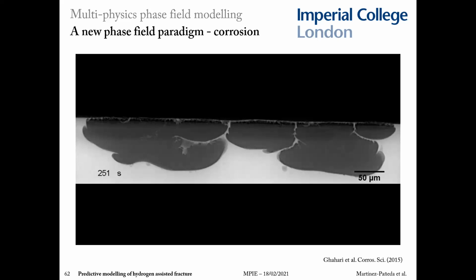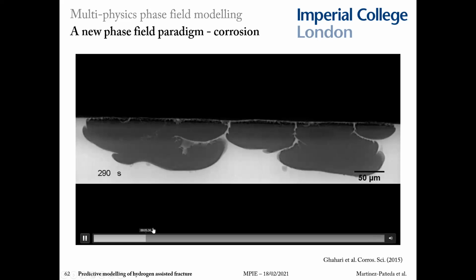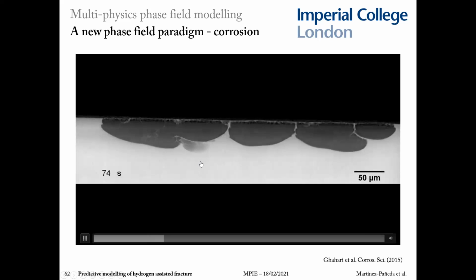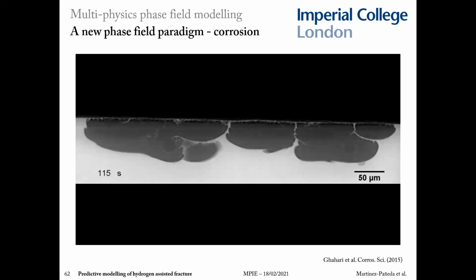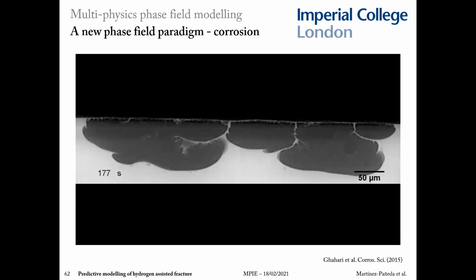One of the biggest challenges from the computational side is capturing how the aqueous electrolyte solid metal interface evolves. You can see in the video, which is a synchrotron analysis of corrosion in stainless steel, how pits form, how they interact, and under certain conditions transform into cracks. So capturing how this aqueous electrolyte solid metal interface changes in time is one of the biggest drawbacks that has held back our computational capabilities in this problem.